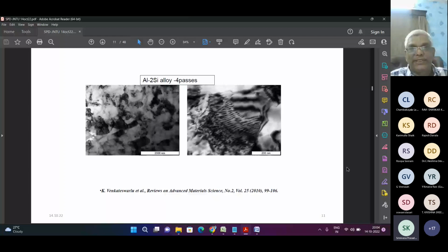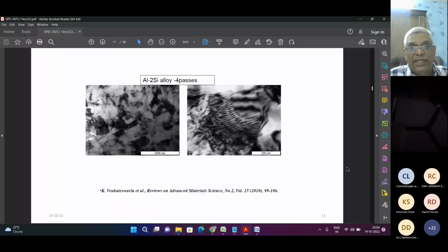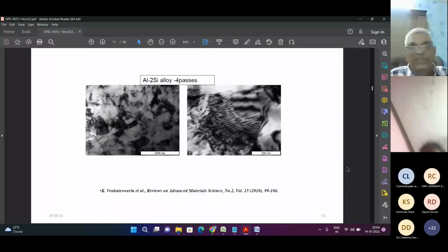So what we are trying to understand is, we have seen the aluminum-scandium and aluminum-magnesium-lithium alloys with different compositions. You can see we have studied the TEM images of the aluminum-silicon alloy also. Here you can see that 2000 nanometers is the scale, where you have sizes of around 200 to 300 nanometers. If you put that on the micron bar, the average grain size will be less than 1 micron.